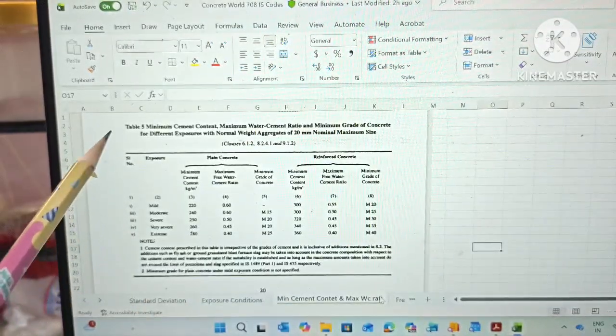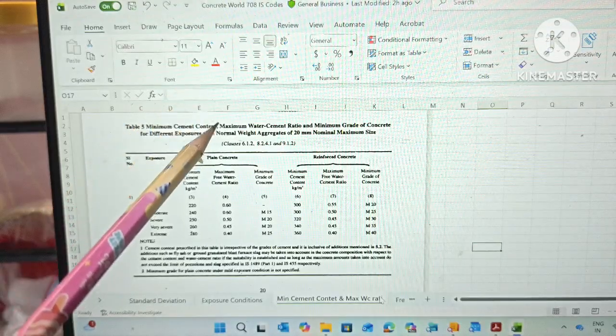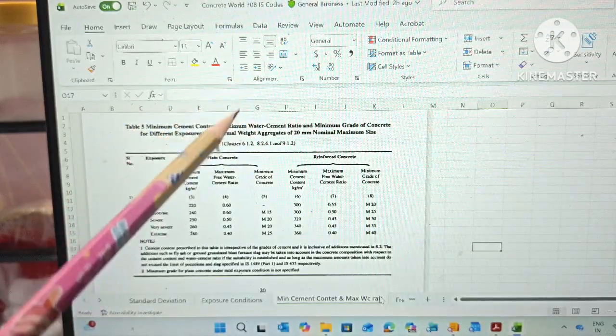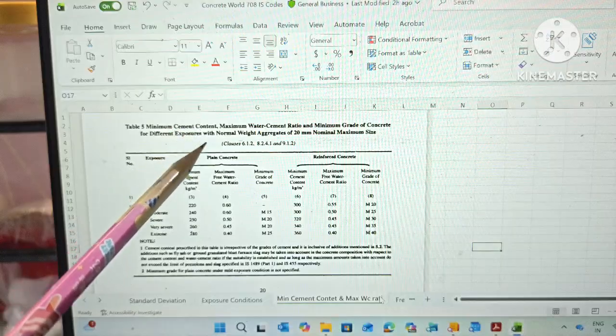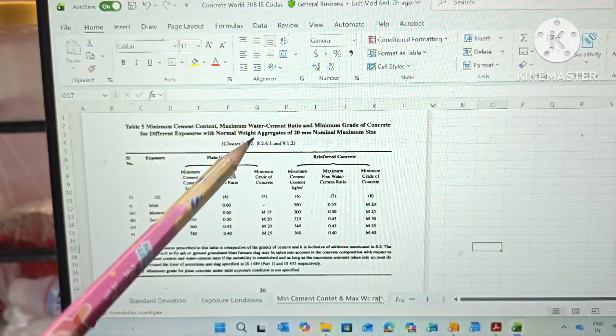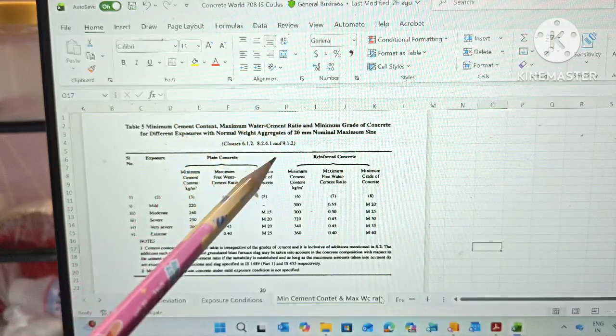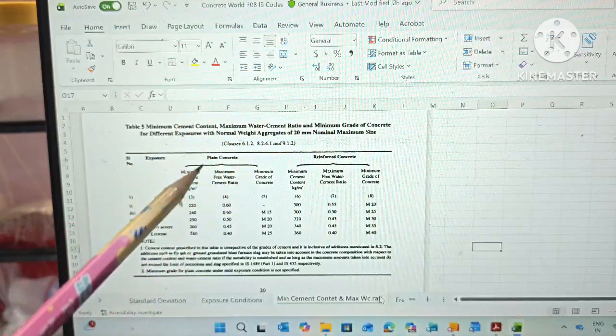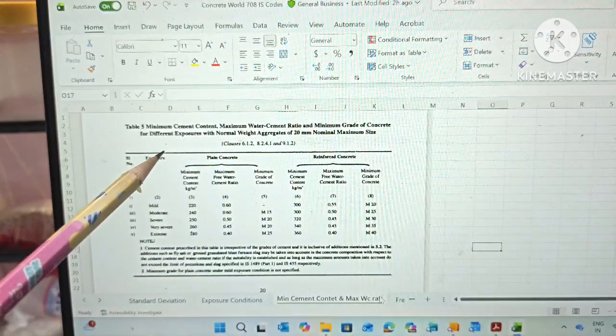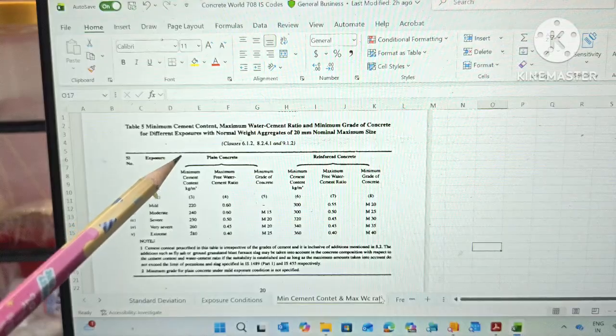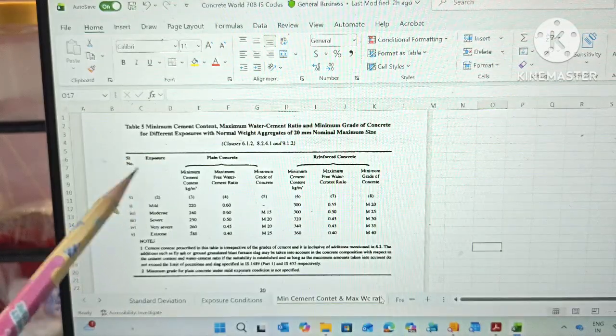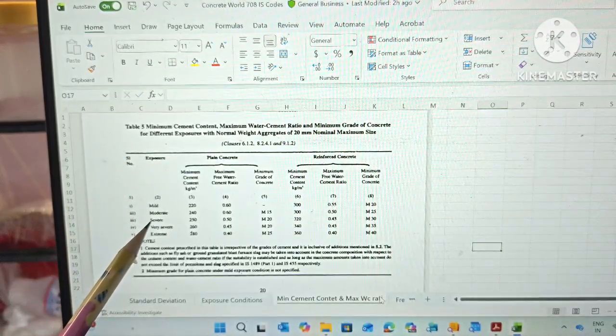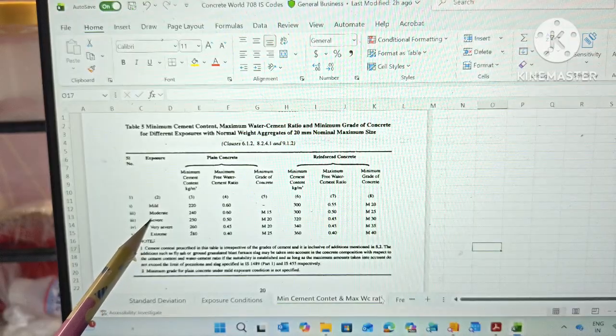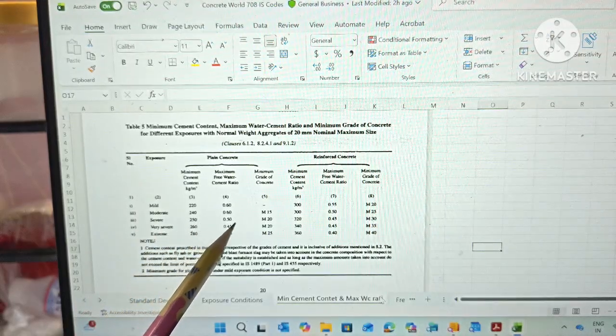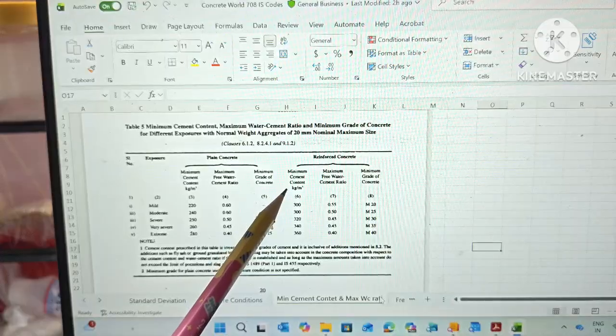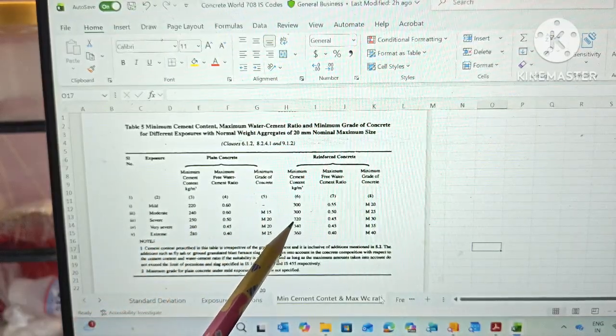Friends, you can see this Table number 5, minimum cement content, maximum water cement ratio and minimum grade of concrete for different exposures with normal weight aggregates of 20 mm nominal maximum size. In this table you can see what the minimum cement content, the maximum water cement ratio, and the minimum grade of concrete can be. Since our exposure condition is severe, if we go along the line of severe, the minimum cement content required is 320 kg.